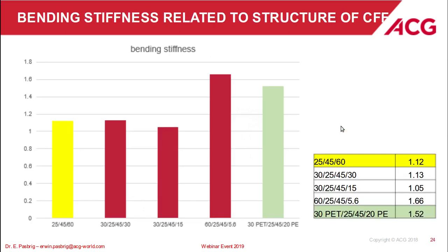Related to the bending stiffness, the structures we have discussed, we have the yellow bar is standard material, 25, 45 to 60 PVC. Next to this, you see the material 30 and 15 micrometer PVC as the sealing layer. More or less it's the same. If you have all three materials in your hand, you won't find a difference in the stiffness of the laminate. Then the material with 60 PVC on the outer side is much more stiff related to the bending stiffness compared to the standard. The reason is that the bending is done from the outer side, so from the PVC on top of the OPA, so the stiffness is increasing. If you compare it, the stiffness layer is on the inner side, and the same for this material with polyester on the outer side with polyethylene as a sealing layer.